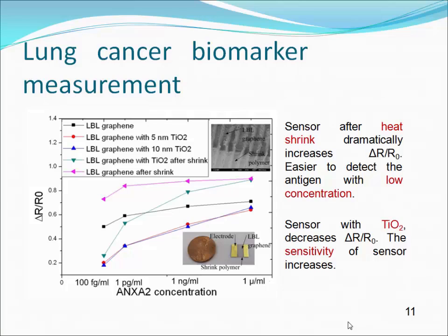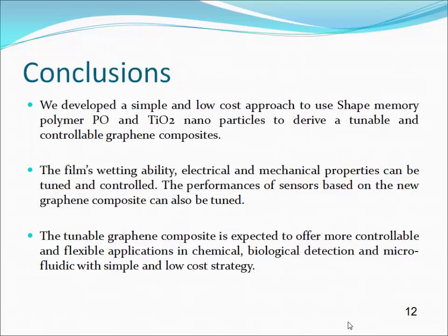So if we combine the heat shrink and titanium oxide layer together, the green curve, our sensor will have good sensitivity, and it also can be used to detect the antigen with low concentration. In a nutshell, the heat shrink can increase the signal of the sensor, and titanium oxide nanoparticle can increase the sensitivity of the sensor. Conclusion.